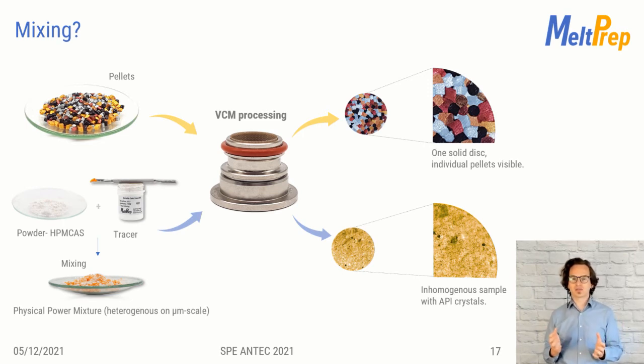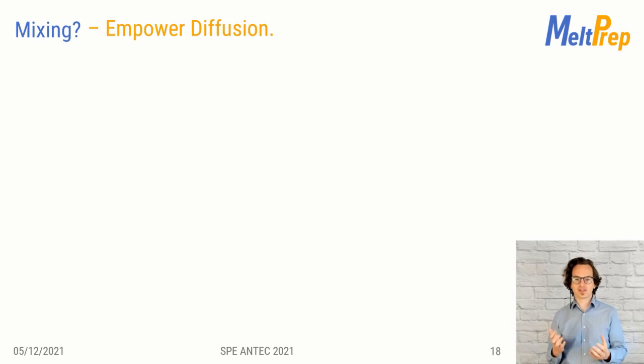This can be done by using powders with a smaller length scale instead of pellets, enabling very powerful mixing via diffusion. We used an orange color dye on HPMCAS powder as a powder blend to illustrate that. As a result, a good fraction of the color tracer already diffused inside the polymer disc, but there are still some agglomerates visible. That's why homogeneous powder mixtures as a starting material are so crucial for our process when homogeneous single-phase results are desired. To improve homogeneity, we have to empower diffusion by reducing the length scale further.